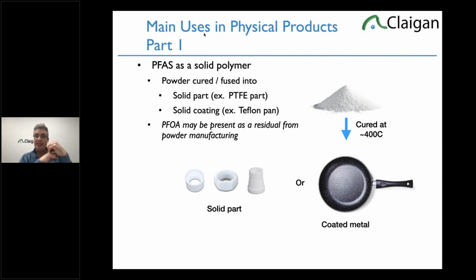So the intentionally added chemicals, PTFE. PFOA may be present because it can be used as a processing aid, as a surfactant in the manufacturing of PTFE, and has a huge impact on controlling the size of the PTFE powder. But C8, you can use C6, the smaller version, which is not as regulated, or other options. And now that they know it's a problem, the facility can actually scrub it out at the powder level for the most part. So if you're reporting for Maine or the US, you're reporting the PTFE, because you're intentionally adding it. The PFOA is not reportable in Maine because it's not intentional.